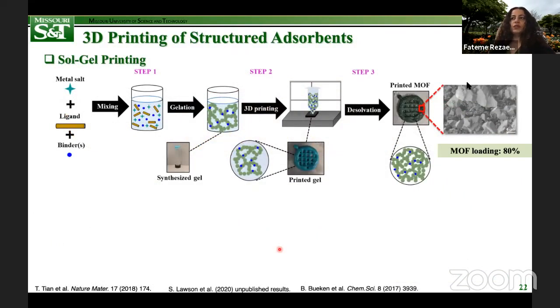Moving on to sol gel printing approach. On the basis of previously reported sol gel approaches for producing hierarchical MOF scaffolds, we initially hypothesized that MOF monoliths could be produced by gelating their precursors, followed by printing and then heating the as-synthesized scaffold to coordinate the linker metal complex. In this method, irregular nanoparticle packing during gelation and printing steps leads to highly loaded MOF monoliths with hierarchical pore systems featuring both intraparticle micropores and also interparticle mesopores.